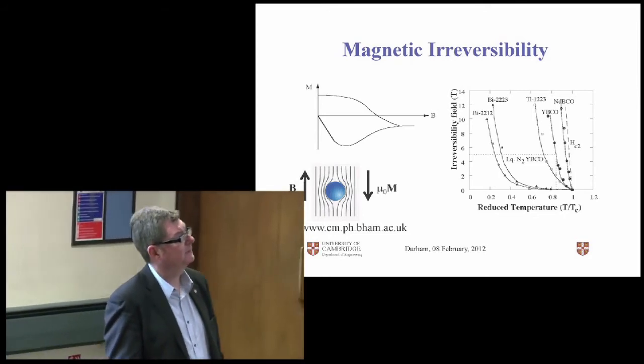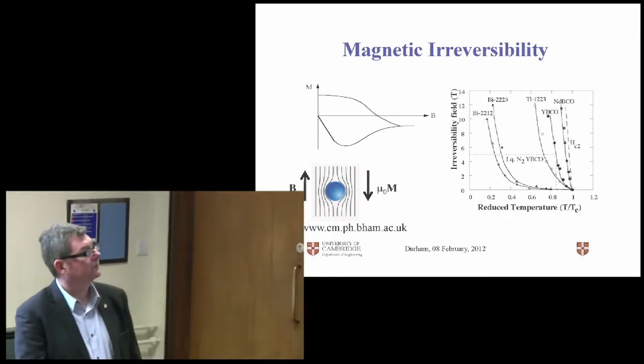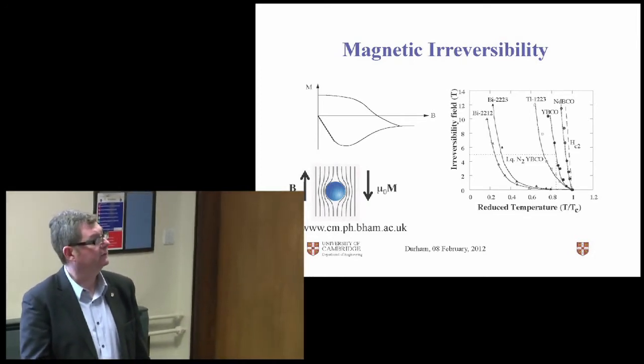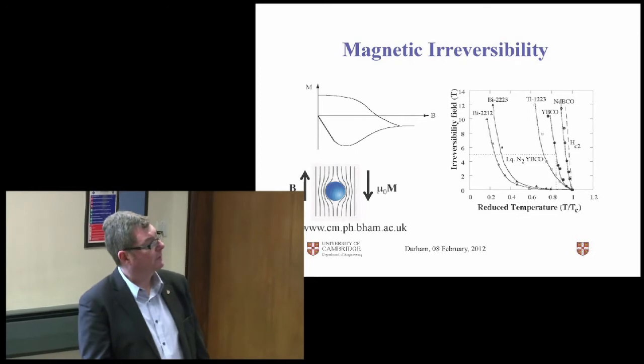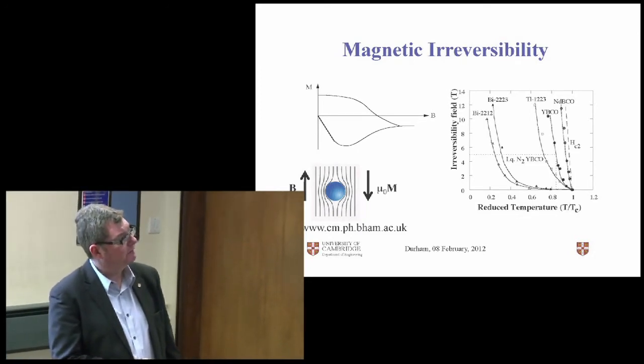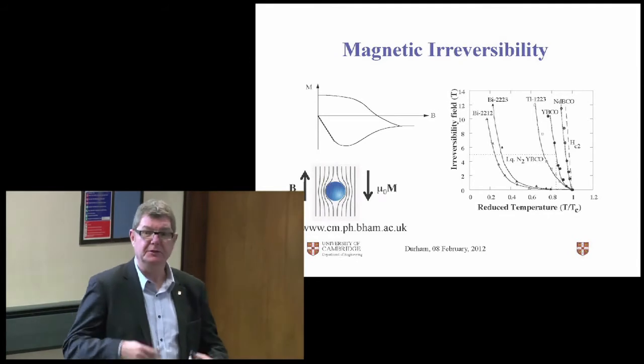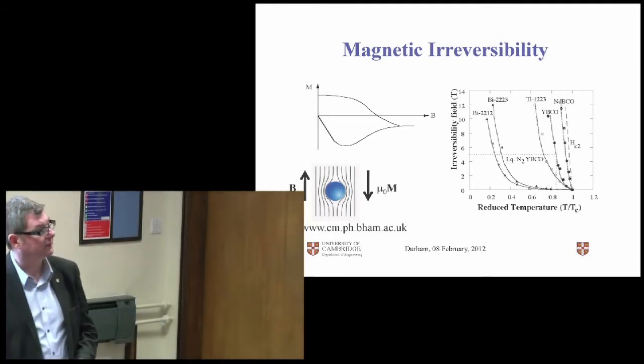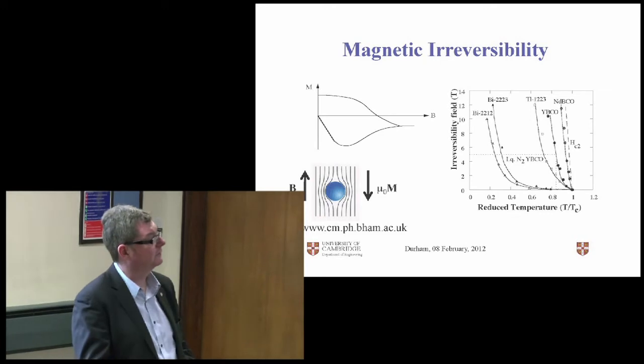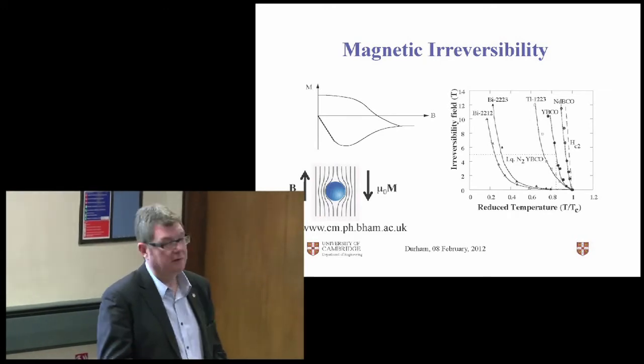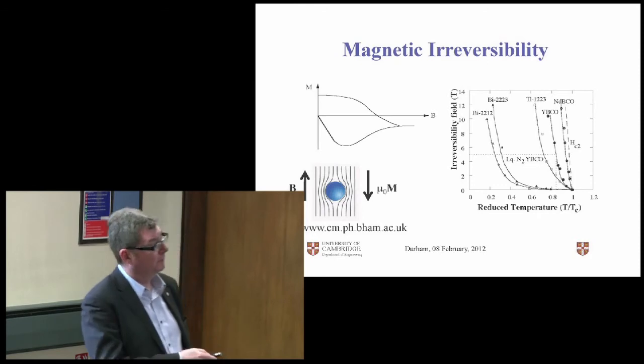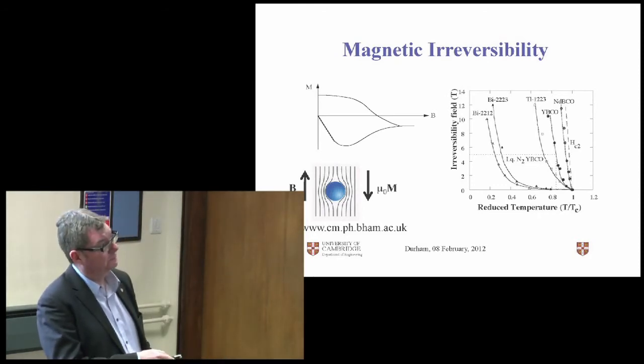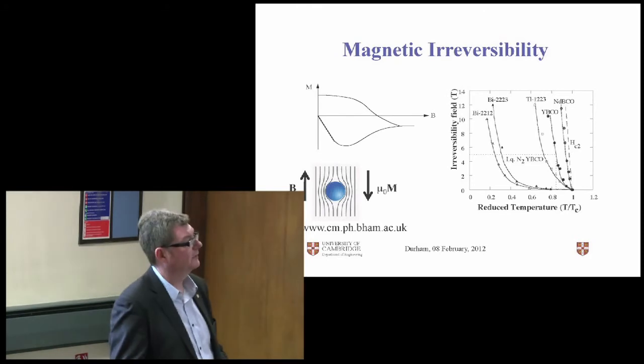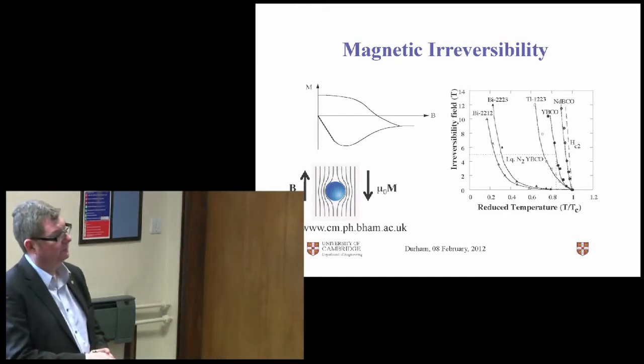Okay, so to say something about magnetic irreversibility, this is the equivalent of the BH curve or the MH curve for permanent magnets. So we apply a magnetic field to our superconductor, and it's diamagnetic, so we induce eddy currents on the surface of the superconductor that resist the application of the field. And if there are no demag effects, and there always are, but if there aren't, if we were to make these units right, so we'd have to multiply this by mu naught, this angle would be 45 degrees. So the superconductor would generate an equal and opposite magnetic field. So I'm just representing that here.